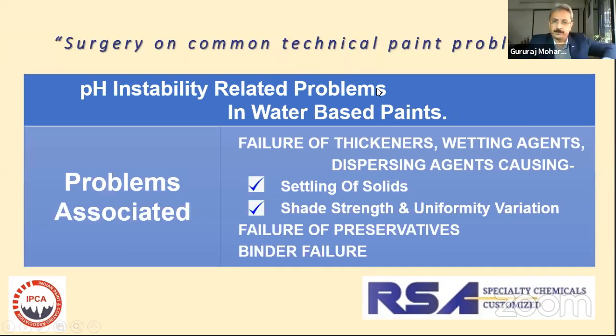So starting with water base, what are the problems that are associated with pH instability? The pH, mind you, doesn't change overnight. It takes a couple of weeks or months, maybe 3 months, 5 months, 6 months, depends. We don't know. It's unpredictable. But pH can change, and when it changes, it does affect the paint function very well.